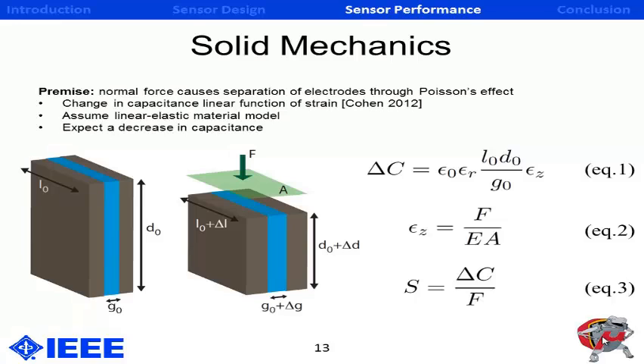Earlier I mentioned the importance of gap size, which is G naught. Changing capacitance is inversely proportional to G naught. So it's important that G naught is as small as possible, which can be tailored thanks to our fabrication process and directly controlled. We assume a linear elastic material model, which should be valid for low strains, as you see in equation 2. And equation 3 is just sensor sensitivity, which we define as the change in capacitance as a function of force. Based on our design, we expect a decrease in capacitance as force is applied.